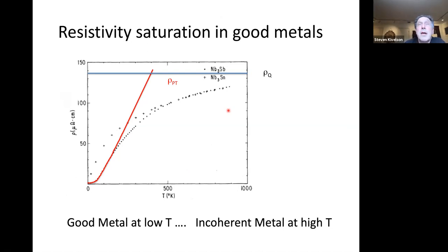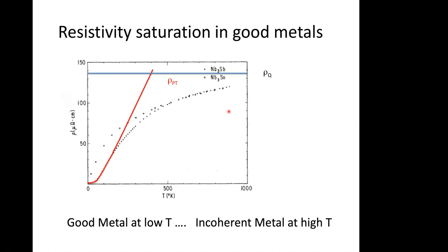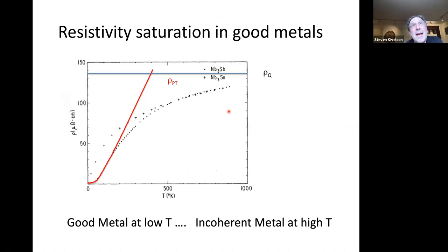Okay. So in order to lose quasi-particles, you need that 1/tau should be bigger than the temperature, or the energy at low temperature if you're doing a finite energy experiment. Exactly. So in that sense, copper at room temperature is an incoherent metal. The resistivity is linear in temperature, and the quasi-particle scattering length is linear in temperature. So at least it's marginally coherent. The width of the quasi-particle is equal to its energy. However, Boltzmann transport theory works beautifully. For an incoherent metal, what I mean is that the mean free path must be comparable to its Fermi wavelength, or the scattering rate must be on the order of the Fermi energy. So that's what my incoherent metal is. There's no emergent scale here.